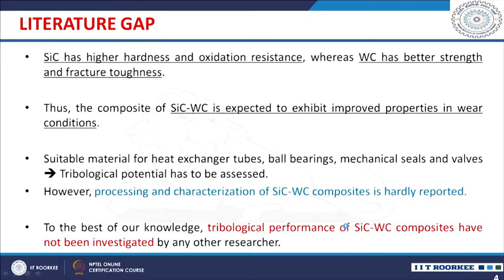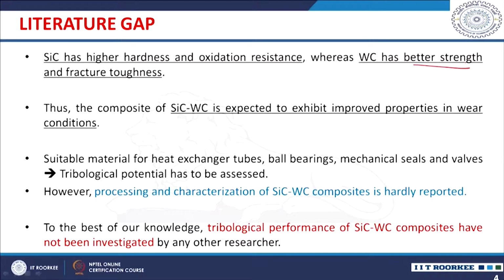However, our literature study indicates that such a material has not been studied for its tribological behavior. Particularly, silicon carbide has higher hardness and oxidation resistance, whereas tungsten carbide has better strength and fracture toughness. So, the composite of silicon carbide tungsten carbide is expected to exhibit improved properties in wear conditions.